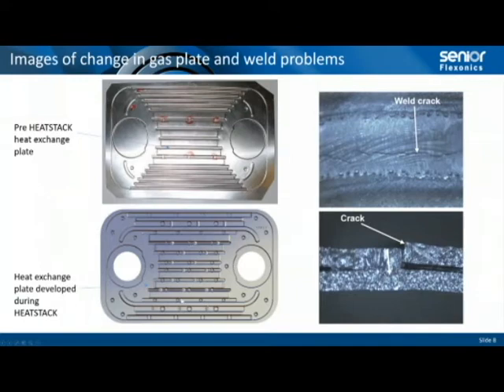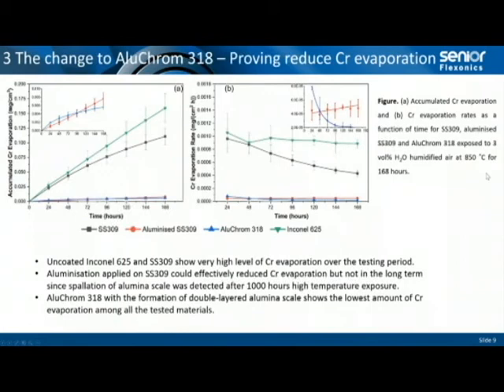Here we can see what the pre-HEATSTACK plate looked like and what it looks like with the AluChrom for HEATSTACK. We also picked up cracking in the weld on the AluChrom initially, so you can see here we're actually cracking in the middle of the weld and sometimes cracking right through the weld. So again, that's all down to tooling and parameters to alleviate that problem. But once we developed that, we had no concerns with that, and had a very high, I think it's 97% right first time when we were laser welding these together. So if I pass you to Kun for 2 sheets.